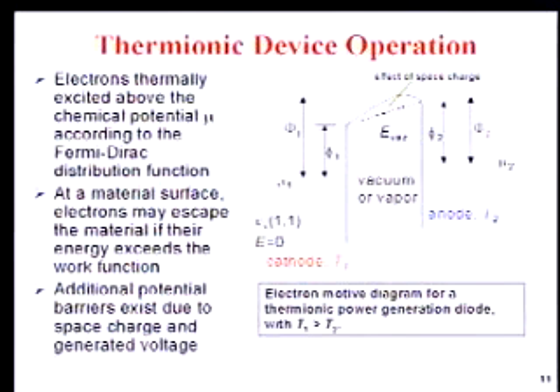This is the way that a thermionic device would work. We heat up a cathode, and electrons in the cathode have to be excited above the Fermi level, above the chemical potential, all the way over through vacuum or vapor. Sometimes we put vapor in here to minimize space charge effects and lower work functions. And then they land on the anode side. Now, there's also a reverse current, and that's going to be important in a minute. There's a reverse current from the anode to the cathode because there's no way to stop these electrons if they have sufficient energy. But we keep the anode at a cooler temperature, so there are fewer electrons moving across.